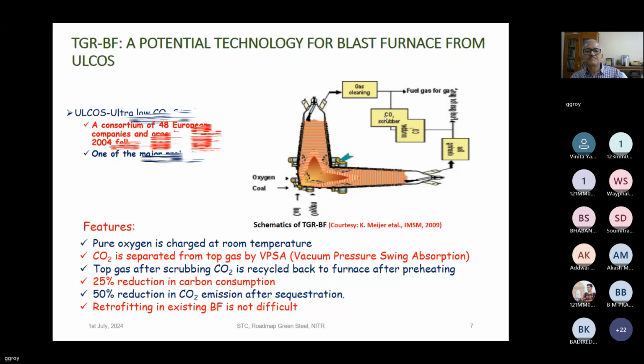CO2 is separated by VPSA, vacuum pressure swing adsorption. Basically, you have a CO2 adsorbing material that adsorbs the CO2 under normal pressure at 1 atmosphere. Then in the next cycle, if you reduce the pressure, you can take out the CO2 and liquefy it, and do whatever you want. So the separation is done by VPSA, and the top gas after scrubbing is recycled back into the furnace. In this way, the process becomes highly carbon efficient.